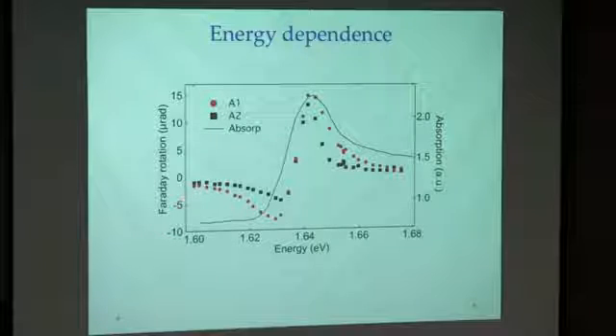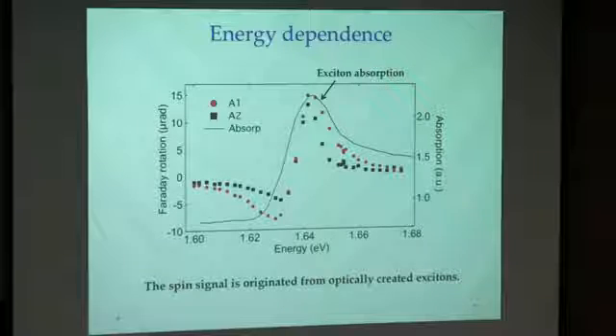So basically, we can get the amplitude of those two components measured as a function of energy. Those points are the experimental data. Basically, we change the wavelength and measure the curve. We change the wavelength by small steps, and we get those points. And this curve shows the absorption. We can see that the signal tracks the absorption peak very well. That confirms that we have a spin signal that originated from the excitons.